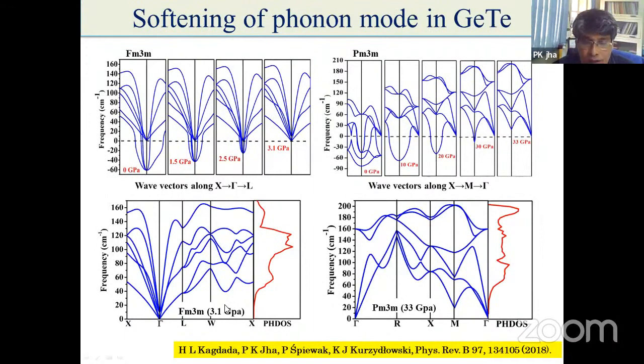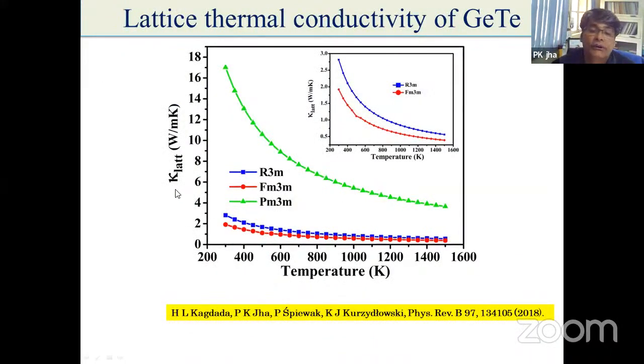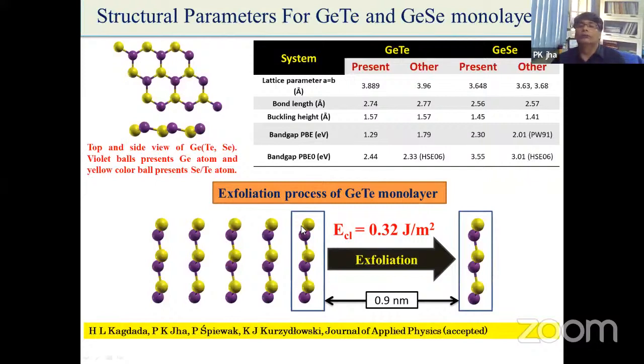Cubic at 3.1 has real phonon modes, a stable structure. Similarly, for Pm3m at 33 GPa, it is stable. So here you can see the lattice thermal conductivity for all three structures, and you can see that the minimum value for the lattice thermal conductivity is, of course, for the Fm3m. But at normal condition, it is not stable. Therefore, we can say that even for the R3m, the lattice thermal conductivity is much lower.